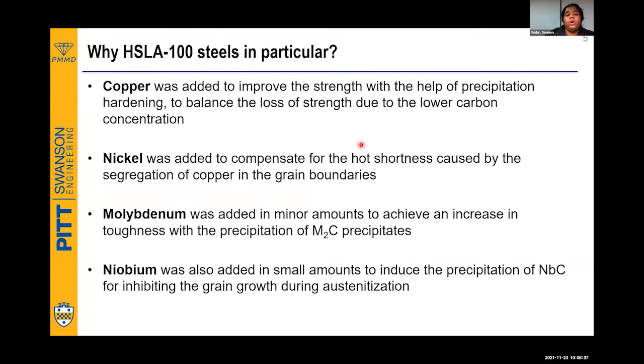And finally, we also add molybdenum for precipitating another type of precipitates, which are called the M2C, where M corresponds to molybdenum. So this is one type of carbide. And in order to precipitate another type of carbide, which is commonly found in the steels, we add the niobium, which is going to precipitate the niobium carbides. And these are called the pinning particles. That is, they're going to sit in the grain boundaries during the austenitization process, and they're going to inhibit, that is typically stop the grain growth. So that's why niobium is added.